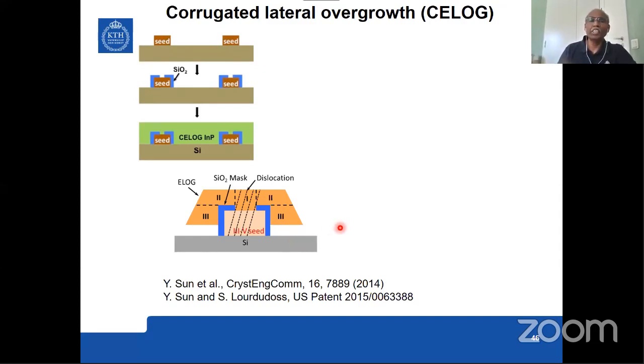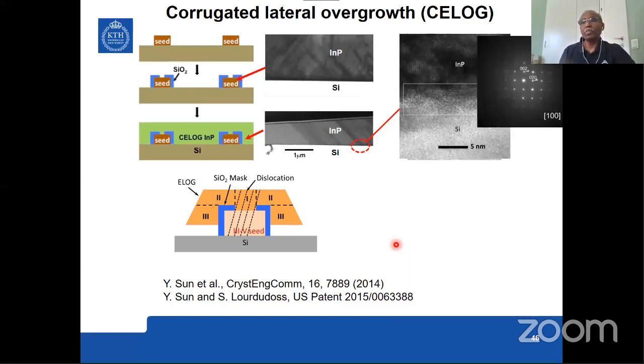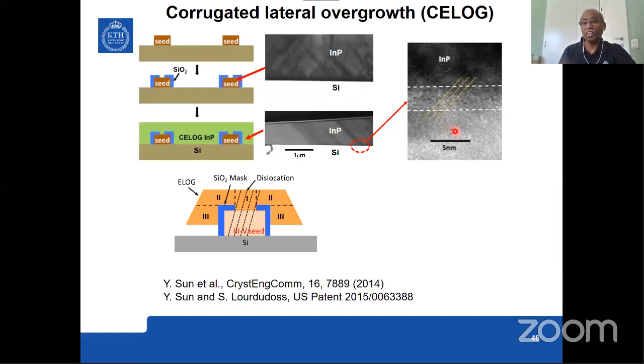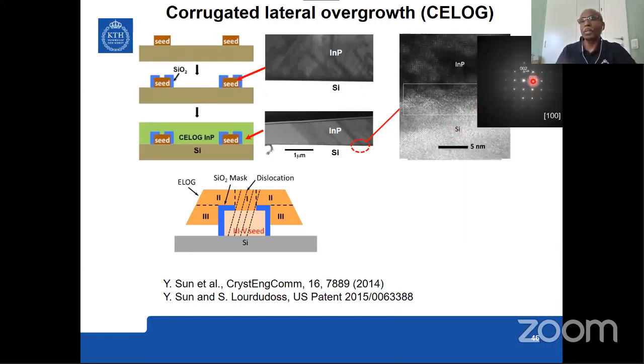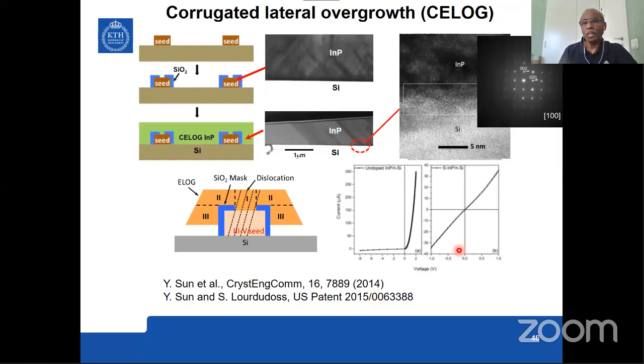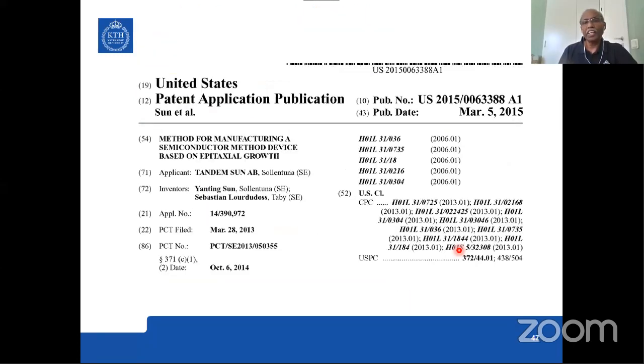So actually it is a kind of epitaxial bonding, because since our technology is completely selective, there is no nucleation here. So everything is coming from here, and the growth will proceed downwards, and it will have an interface with silicon. So in that way, you can have some III-V material directly on silicon, just like bonding. So we have demonstrated, and this is the interface between silicon, and here is the TEM, the X-ray diffraction picture, and we can see the signature of both silicon and indium phosphide. And the electrical characteristics also show it as a rather good interface. And again, it has been patented.